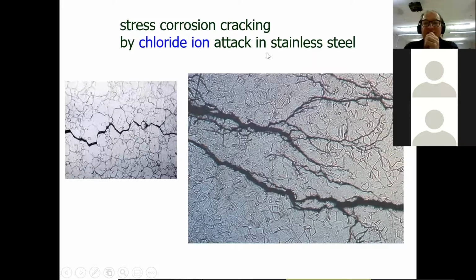And this is in stainless steel, and it's been caused by chloride ions. So I think I've already mentioned to you, I think you know this already now, that stainless steel is very susceptible to corrosion by the presence of chloride ion. In particular, if it's stressed like this is, you will get stress corrosion cracking as a result of the attack of chloride ions. So stainless steel is very susceptible to stress corrosion cracking if it's in contact with something aggressive like chloride ions. If it's just in contact with fresh water, it's probably going to be perfectly okay, maybe no problem ever. Or steam, fresh steam, it's probably okay. But the moment you get chloride ion or some other ion in there, then you have the problem.